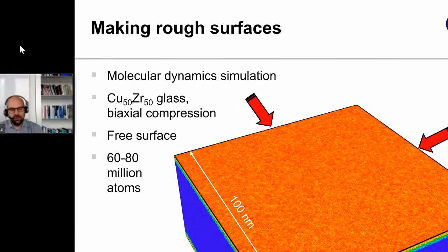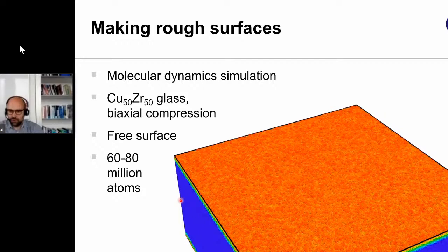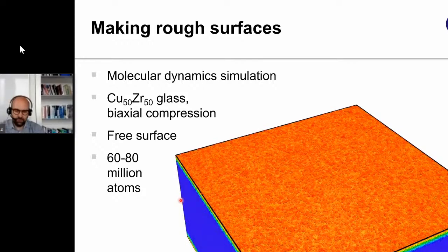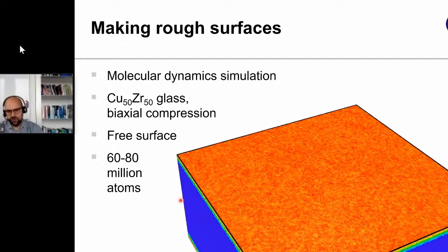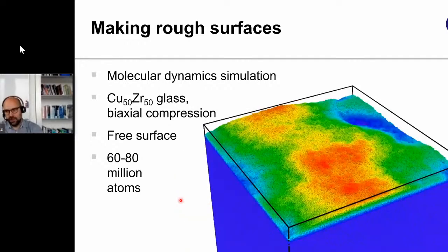We simply compress it along the axes indicated by these red arrows. So again, in this laminar idea of deformation, what should happen is that the slab simply becomes thinner, and this surface should move up. But let me run this calculation for you. What you see is that even though this material is perfectly homogeneous, the surface has become rough after this calculation. So there seems to be something intrinsic to the deformation process that leads to surface roughness.